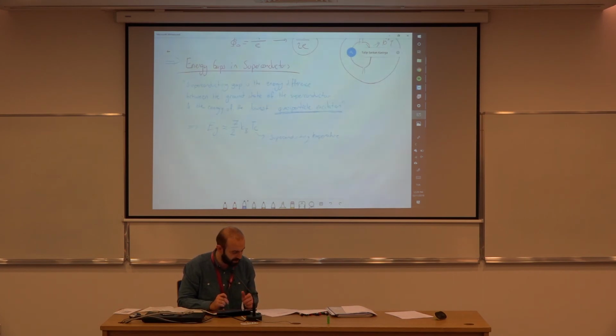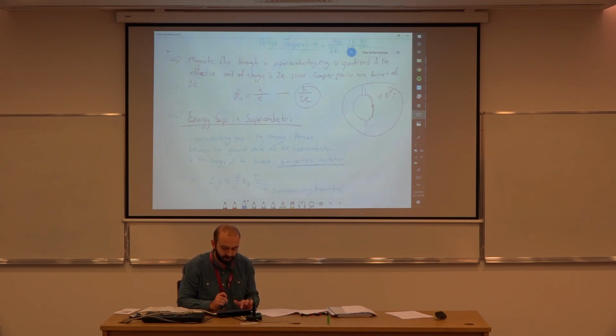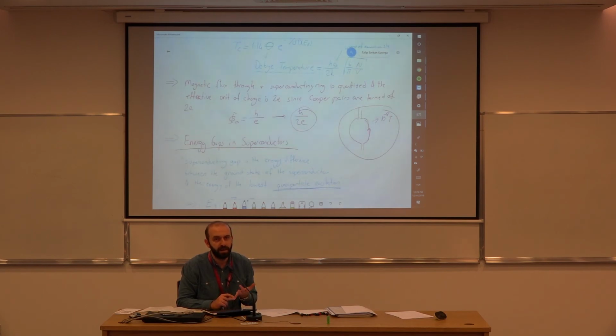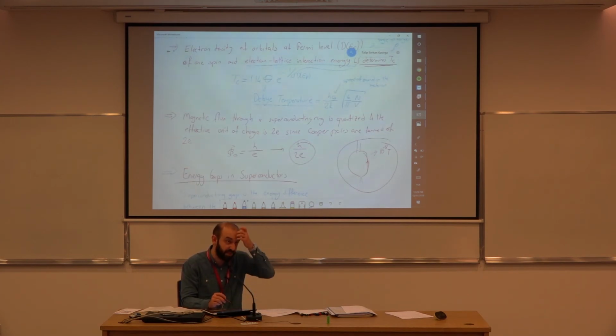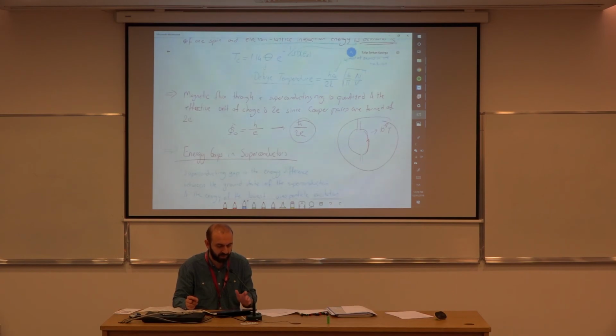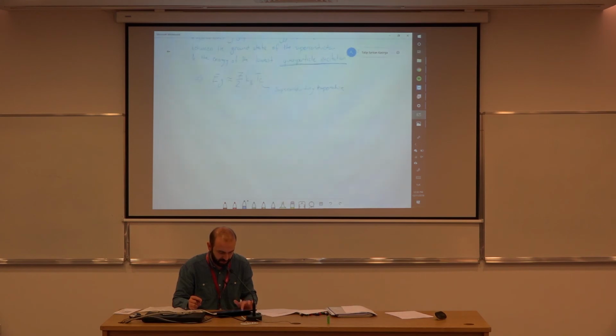So I'm not sure if it has anything to do with not observing superconductivity in good metals, good conductors like copper, silver, gold. We don't observe superconductivity in these materials, and they are the best conductors we know, so they have very low rho, which sort of indicates that this U interaction between the electron and lattice is relatively smaller compared to the other metals. So probably one of the reasons why we don't see superconductivity in these materials is the strength of that energy.